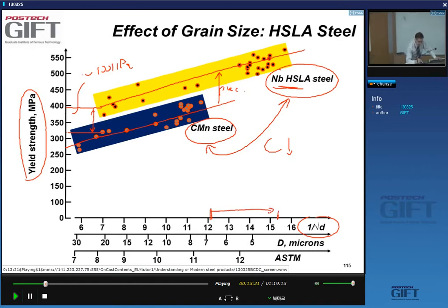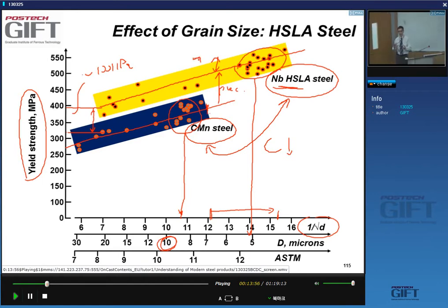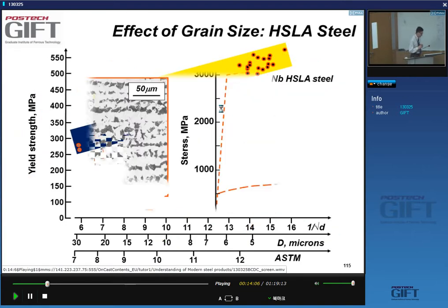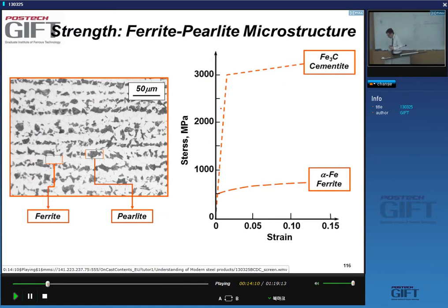Yes? You see here these carbon manganese steels, yes? It's very difficult to get, you see here there is a cloud of data points that corresponds to a grain size around 10 micron, yes? Here, with this HSLA steel, we can drop the grain size to 5 microns. So we get an additional increase in strength, which is due to grain size, okay? So in these HSLA steels, you get both grain size refinement and precipitation hardening, okay? Two strengthening mechanisms occur at the same time. All right, so,